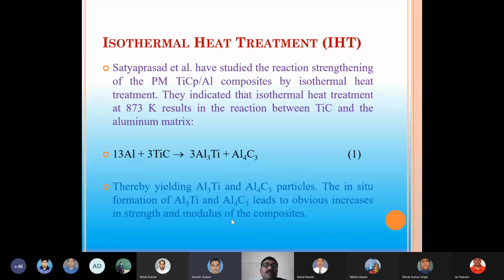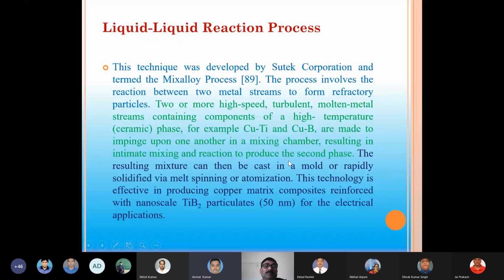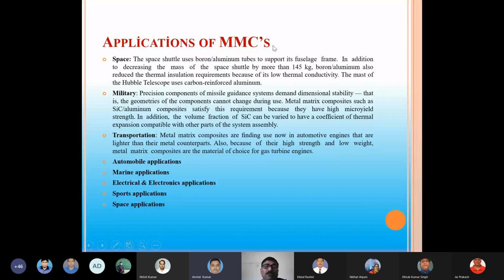Isothermal heat treatment process: here aluminum will react with titanium carbide, forming titanium aluminide and aluminum carbide, as in equation 1. This holds at the lower temperature, but at the higher temperature this titanium aluminide will decompose and the titanium will separate out, and this titanium will react with the carbon and form titanium carbide. Then the liquid reaction process. Now we'll talk about the applications.